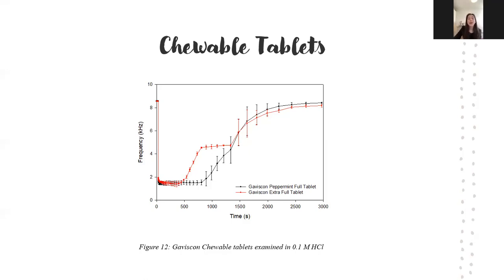The deaggregation of both tablet components in unison causes the analysis to be less reproducible, and then it doesn't fully return to steady state due to undissolved excipients in solution, due to that pink side, unlike the peppermint. And there's a difference in mass between these two samples, where there's 1.4 grams for the Gaviscon Extra and 0.8 grams for our Gaviscon Peppermint.